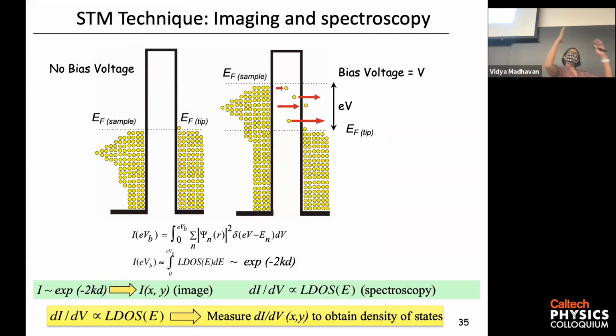Okay, so a very nice pictorial way of thinking about the STM is the following. You can imagine the sample and the tip as basically filled buckets of electrons up to the Fermi sea. When they're both brought into proximity with one another, the two Fermi energies line up, and so there's no tunnel current. When you apply a small potential difference between them, you can lift the Fermi energy of one with respect to the other, and now electrons can tunnel from the filled states of the sample to the empty states of the tip. And you can see actually that the number of tunneling electrons should be proportional to the integrated density of states of both the sample and the tip.